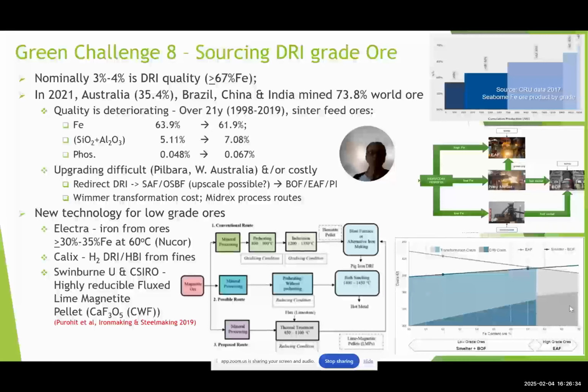So obviously some new technologies are required for low grade ores. Electra is iron from ores that can be as low as 30% iron. It's 60-degree temperature, and Nucor is interested in that one. We have Calix that is doing fines recovery from low-grade ore. And Swinburne University and CSIRO are looking at the highly reducible fluxed lime magnetite pellets. And that process would reduce the process from ore to iron by a whole step and at a lower temperature.